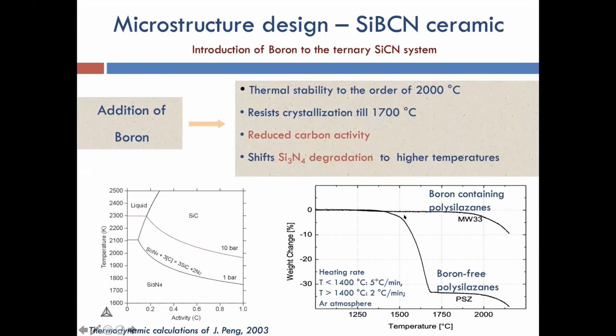What we did was proceed further to add boron into the system. We see a remarkable improvement when we move from a silicon carbonitride system to a boron modified silicon carbonitride system. The boron modified silicon carbonitride system is thermally stable till 2000 degrees Celsius, and completely amorphous till 1700.